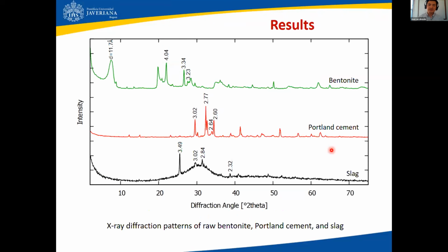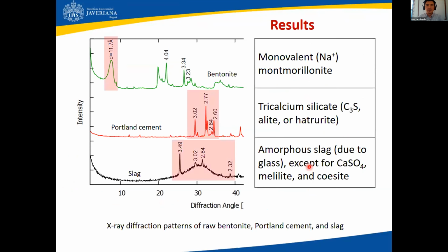So as far as X-ray diffraction patterns, what you're looking at here is the typical representation of X-ray diffraction data. On the x-axis, you have diffraction angle in 2 theta fashion, and on the y-axis, you have intensity in arbitrary units for the discussion. And you can see here 3 patterns, one for the individual raw bentonite, just as received from the commercial provider, Portland cement, and slag, the replacement cementitious material. So what I want you to look at is the main peaks that allow us identification of the main minerals present here.